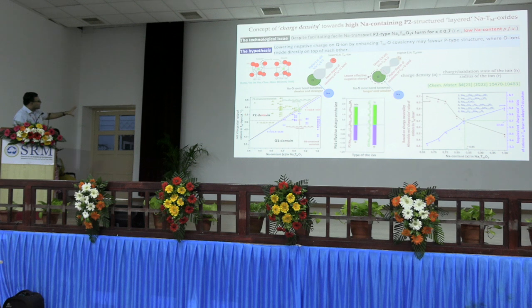So now when we looked at the literature, we found all the materials reported, P2 versus O3, can be separated out in terms of the charge to size ratio and the sodium content. Using this map is very important, because we can figure out that if I want a sodium content of say 0.9, which is very difficult, we have tried, not yet, what is the charge to size ratio that we need so that we design the composition of the transition metal layer. But anyway, what we could achieve was a sodium content of 0.84, which is way beyond the 0.7 per formula unit or 0.67 per formula unit, which are usually obtained for the P2 type structures.